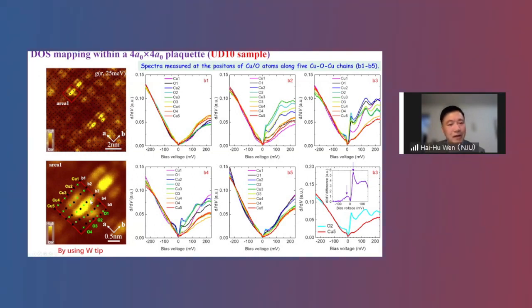Okay, and in that case, you can see this tunneling spectrum. If we measure on the boundary, we don't have this low energy density of states. We see a large V-shaped gap without a low energy density of states. However, if we move into the block, let's say on the central bar, then we see that a low energy density of states comes out clearly with a small gap. And this gap is about 20 meV. This mapping was measured at 25 meV.